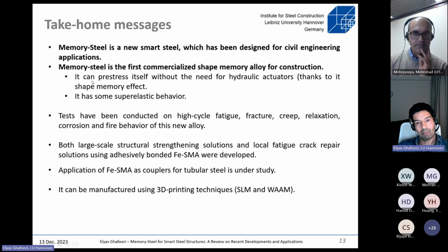It has a strong shape memory effect that gives us the possibility for pre-stressing the structure. It has limited superelasticity. We are working to improve that. And unlike nickel titanium, which the last speaker also correctly mentioned, which is very sensitive in 3D printing, because during 3D printing, some of the elements are gone, evaporated, and then that affects substantially the behavior of shape memory alloy, nickel titanium in particular.